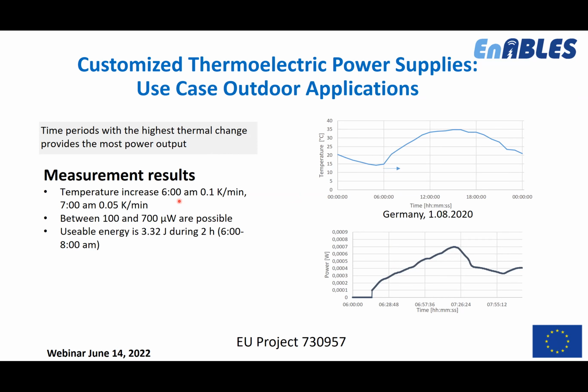At 6 a.m. we had 0.1 Kelvin per minute. At 7 a.m. we had 0.05 Kelvin per minute. And between these 2 hours, this is the output power we could get with the harvester. The power is roughly between 100 and 700 microwatts. So the total energy we could harvest during these 2 hours was 3.3 joules.